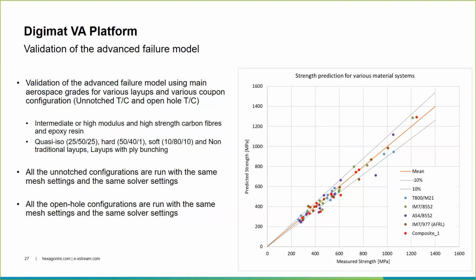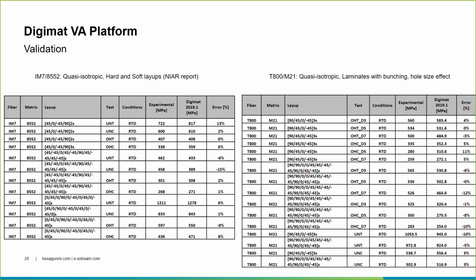If we look at some detail, so a lot of data here. This is the detail for the IM7-8552. So here typically we use the data coming from the NIAR report from the CMH database. And we can localize where we don't have a good result. So like I explained, for the unnotched compression, we have only minus 15% of error, for the unnotched compression test with a soft layup. So that's the most challenging to simulate.